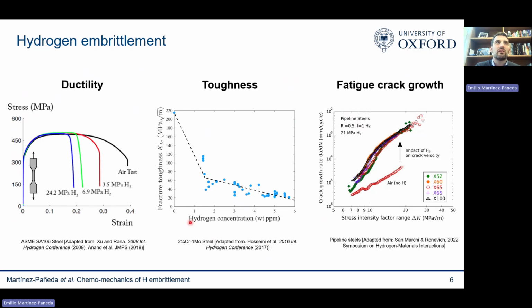In the middle, you see the impact on toughness. That is quite remarkable. This is for a pressure vessel steel, where just 6 parts per million of hydrogen, a tiny amount of hydrogen, takes you all the way from this 220 megapascal square root meter fracture toughness to below 20 megapascal square root meter. So a tiny amount of hydrogen reduces by an order of magnitude the fracture resistance of my pressure vessel steel, going from something very ductile to something that is as brittle as an engineering ceramic.